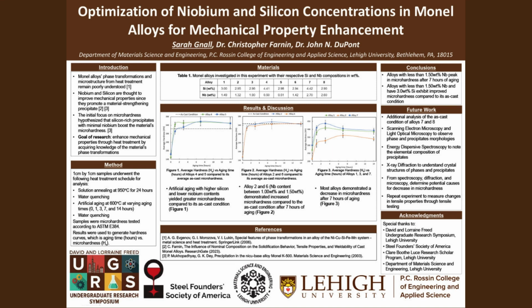It was also observed that these alloys have this dip in microhardness after 7 hours of artificial aging, meaning as aging goes on, the microhardness decreases. More work needs to be done to better understand these results, but we can conclude from these observations that alloys with less than 1.50 weight% niobium peak in microhardness after 7 hours of aging, and alloys with less than 1.50 niobium and 3.0 weight% silicon exhibit improved microhardness compared to its as-cast condition. Future work needs to be done to better understand these results through scanning electron microscopy, energy dispersive spectroscopy, and X-ray diffraction.